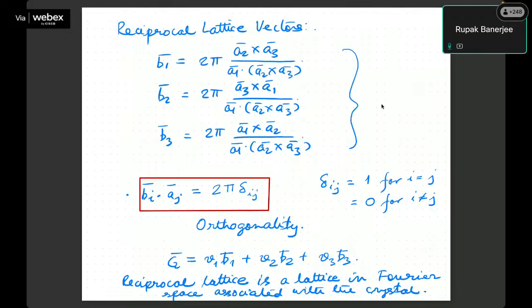Only one condition I have to satisfy, that bi dot aj should be equal to 2π δij. This is a condition of orthogonality, that you are aware that it will only be 1 when i equals j, and it is 0 otherwise. Okay, so whenever it is bi dot ai, it will have value 1, and bi dot aj will give you value of 0. So under this condition of orthogonality, you can create a set of reciprocal lattice vectors from a known set of real lattice vectors, such that you can define a reciprocal lattice vector G, which is nothing but a lattice in the Fourier space associated with the crystal.